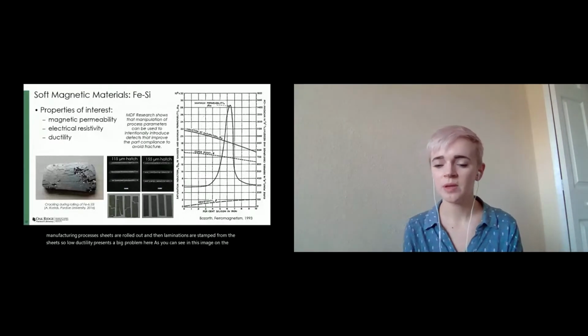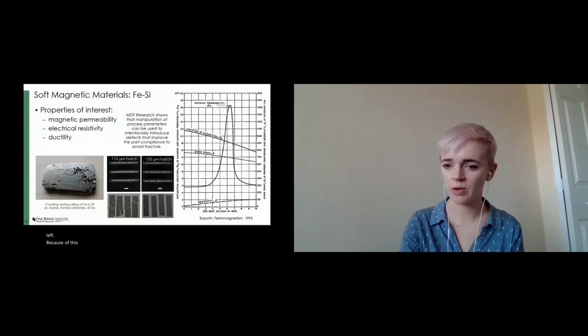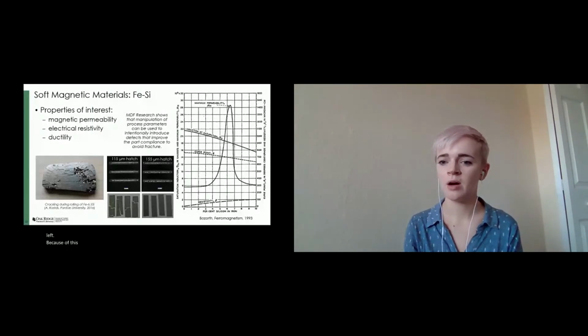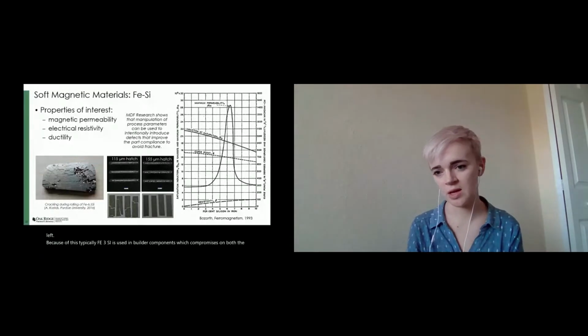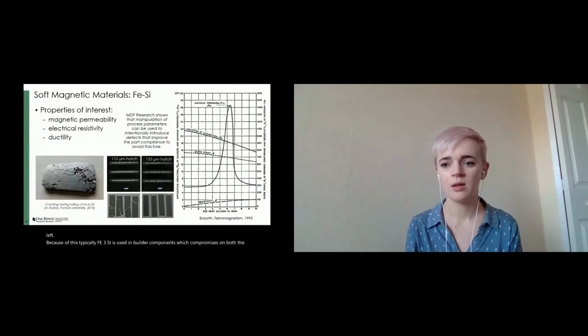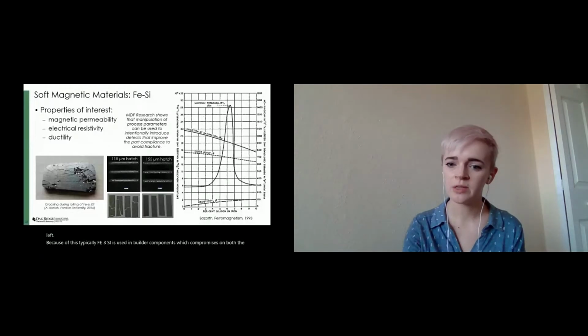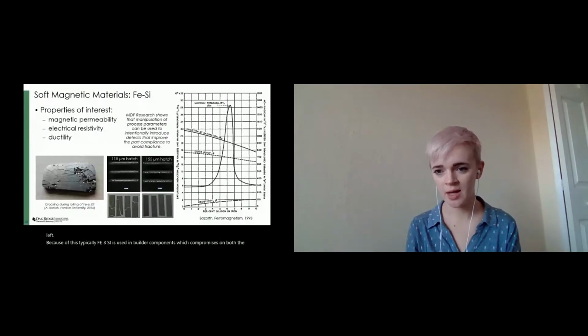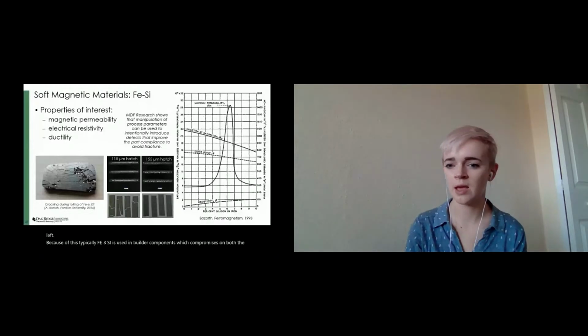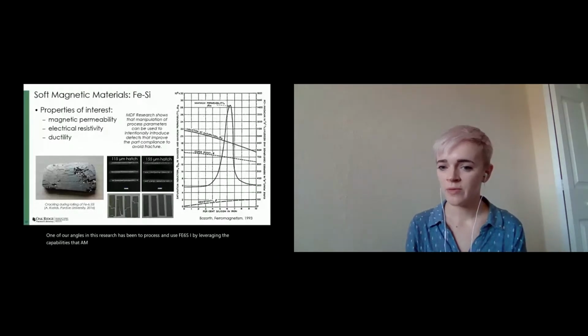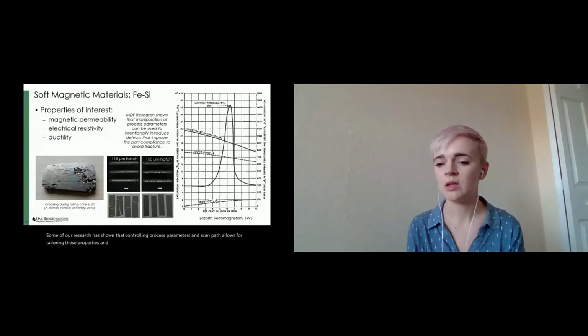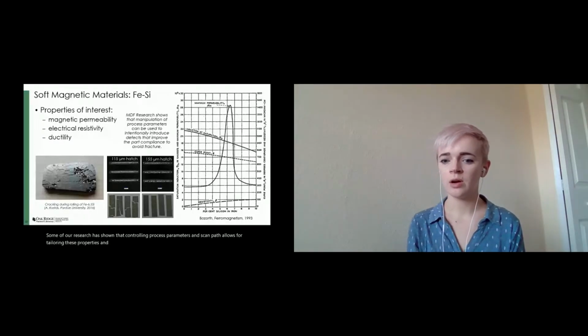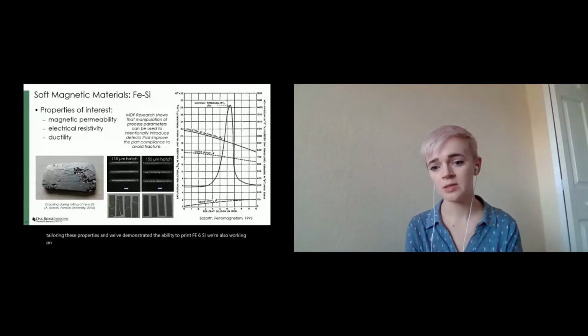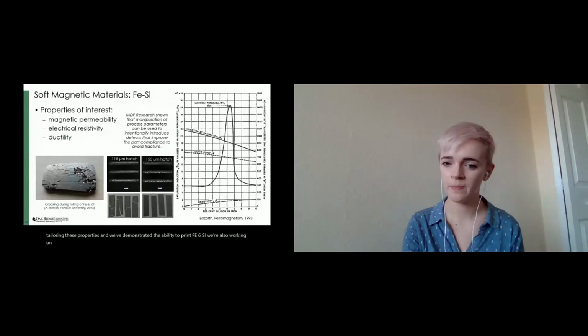Because of this, typically Fe3Si is used in motor components, which compromises on both the permeability and resistivity in favor of the ductility. One of our angles in this research has been to process and use Fe6Si by leveraging the capabilities that AM offers. Some of our research has shown that controlling process parameters and scan path allows for tailoring these properties, and we've demonstrated the ability to print Fe6Si. We're also working on developing Fe6Si alloys that will improve printability further.